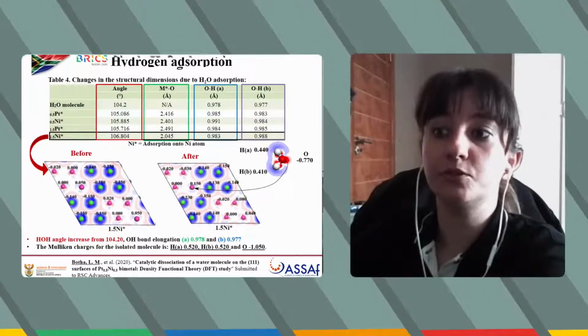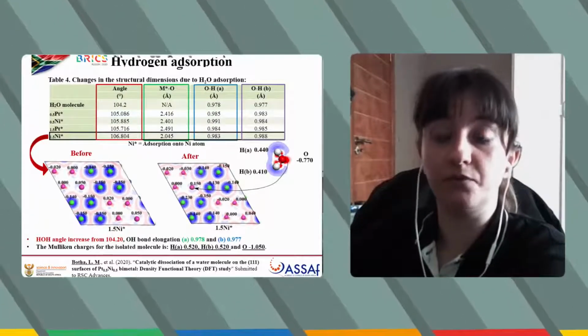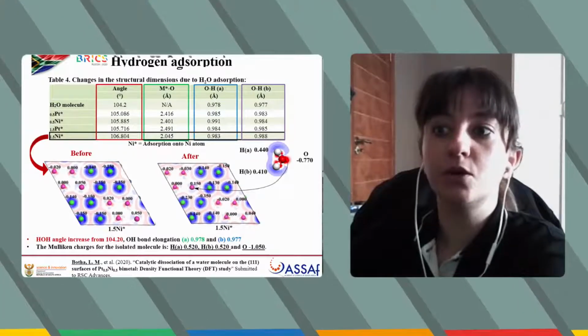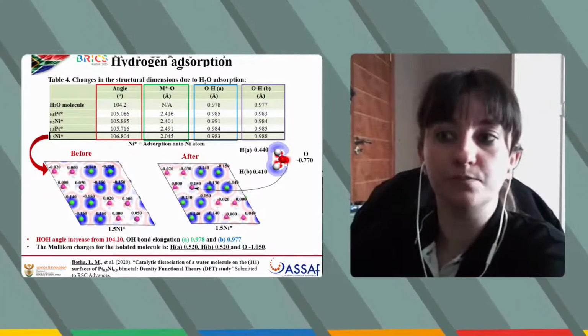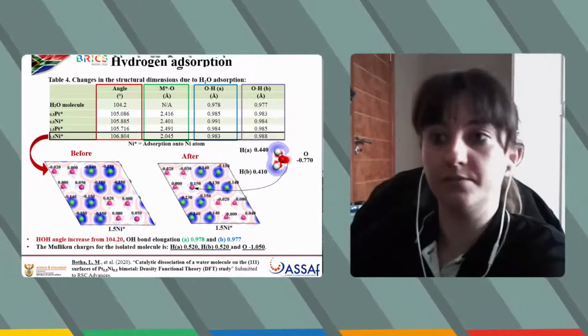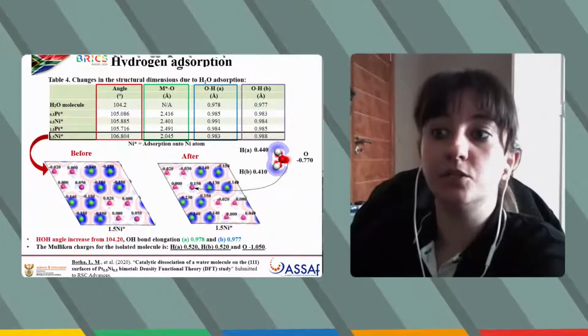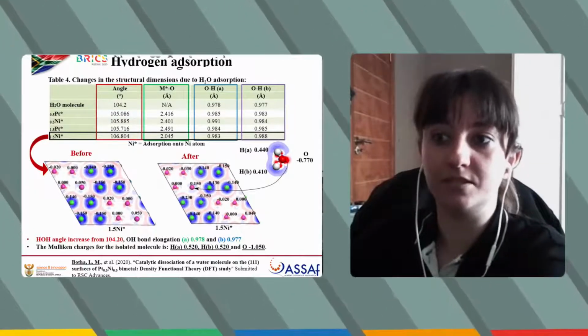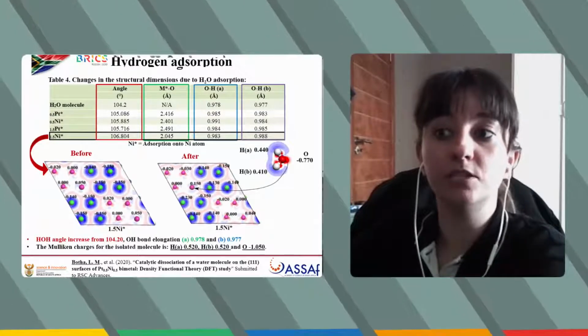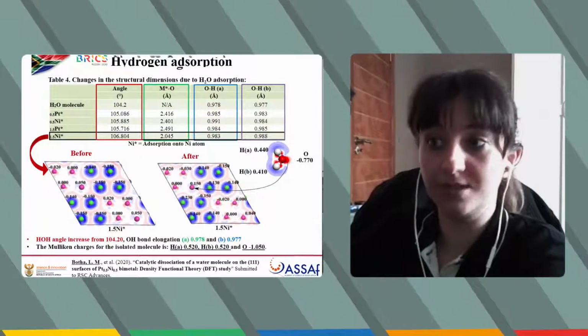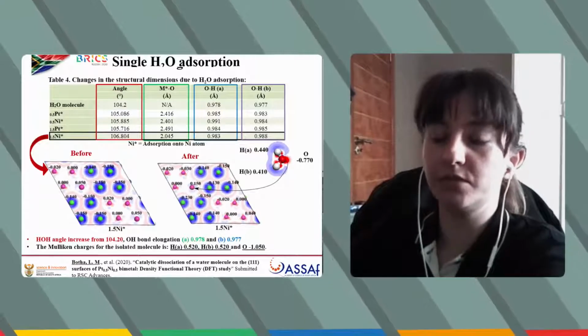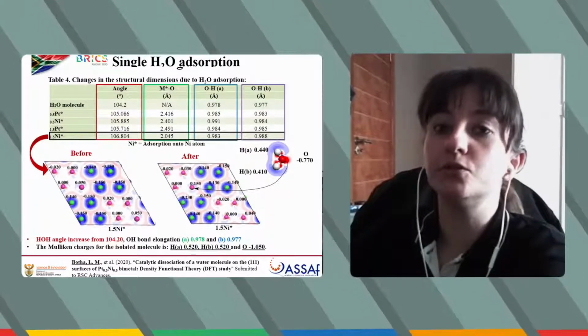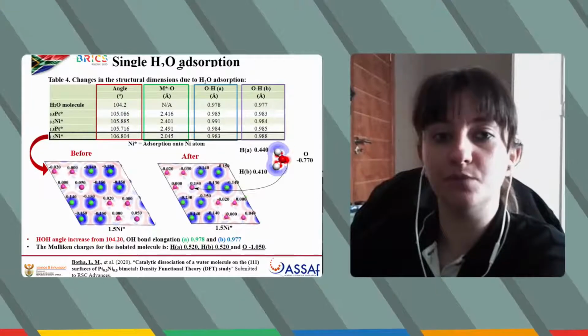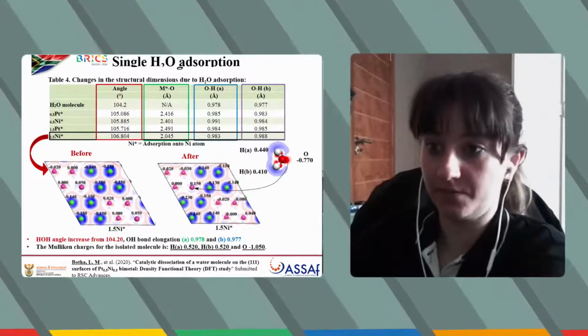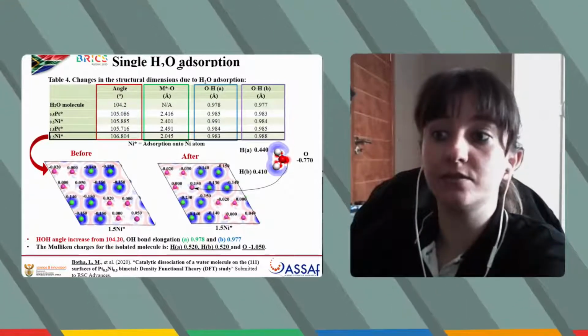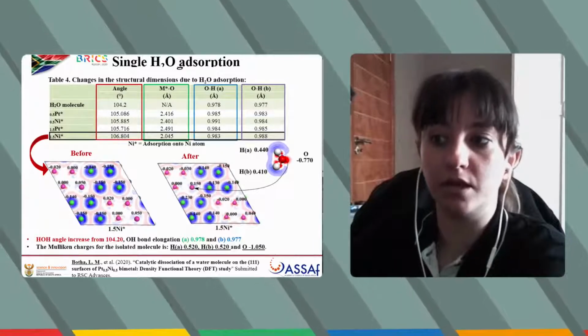The movement of the electrons between the bimetallic surface and the adsorbed water molecule is calculated using Mulliken charges. It's indicated in this figure. If we look at the Mulliken charges of the water molecule and the surface, we observe that the Mulliken charges of the hydrogen atoms in the water molecule decrease from 0.52 to 0.42, and that the oxygen becomes less negative. This indicates that the electrons are moving from the oxygen to the hydrogen.